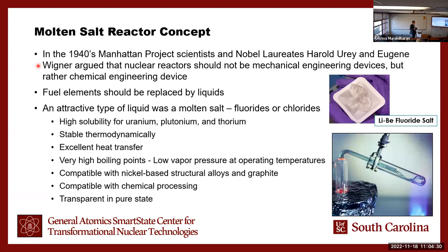And molten salts were really attractive. They have high solubility for the actinides; they're stable thermodynamically. Good heat transfer capabilities; very high boiling points, so they have low vapor pressures. Compatible with the nickel-based structural alloys and with graphite, and they would be compatible with chemical processing, and they're transparent. And here you see a lithium beryllium fluoride salt. It's a solid, and here it's heated up, and you can see it's a liquid, and it's relatively clear. And why do they care if it's clear? Well, that's another mechanism for heat transfer, radiative heat transfer.